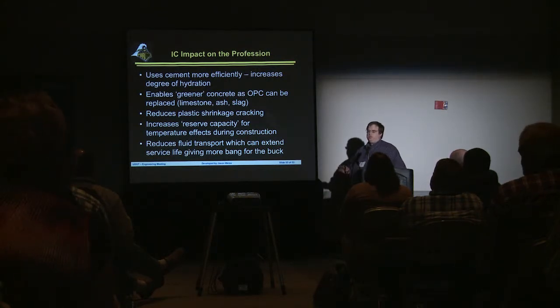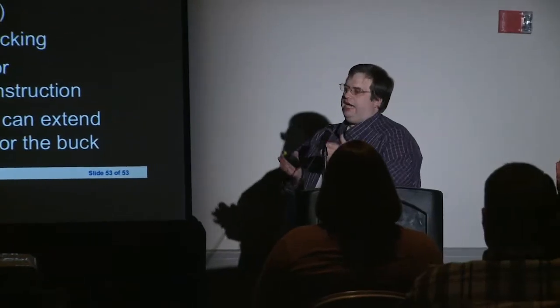Yeah, so the question really is, how do you determine how much lightweight aggregate to use? There's an actual equation to use where we essentially say there's a supply and demand. We say the mass of the lightweight aggregate times the porosity of the lightweight aggregate times how saturated it is is sort of the supply of water that's there. The demand is how much cement you have, how much chemical shrinkage you have, and how much reaction you have. All those are numbers that we know, and it turns out that you want about 7 pounds of internal curing water for every 100 pounds of cement. In a typical mix like we'd be talking about here, we're putting in about 225 pounds of lightweight aggregate to replace the sand. So we're replacing about 25 to 30% of the sand in a conventional mix.